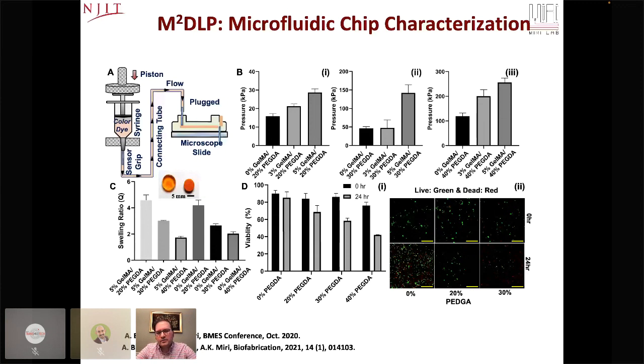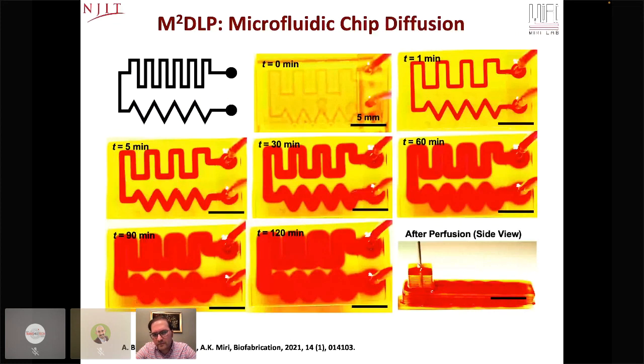And now the next step after showing the biological response, we wanted to see how the hydrogel-based system can help us as engineers to control the biotransport of any transport-based phenomena. And again, the experiment was simple. We wanted to have two specific geometries that people may use for maybe mixing or other characteristics, and then see how the agent, here a food dye particle that's almost micron size, diffuses. We look at how the micron size particles diffuse from the channel into the hydrogel system over a period of 2 hours. And again, the system is polyethylene glycol based, and the diffusion rate again can be controlled by changing the concentration and other fabrication parameters.